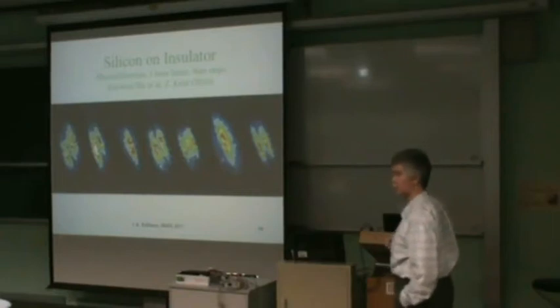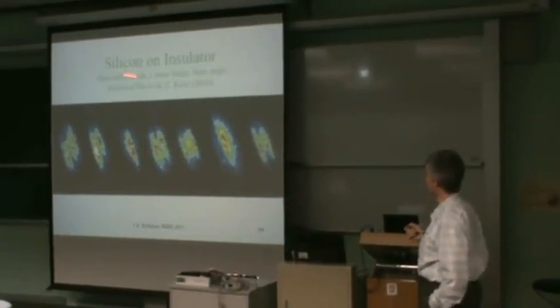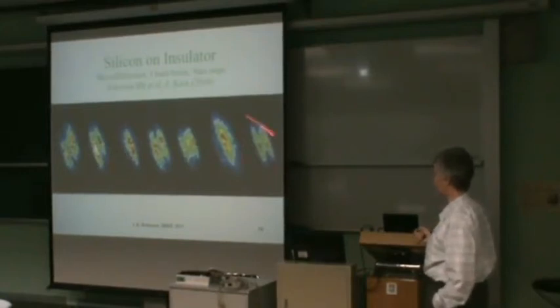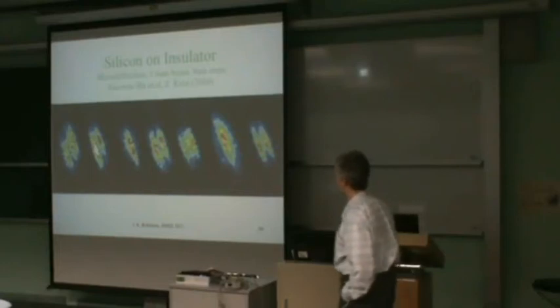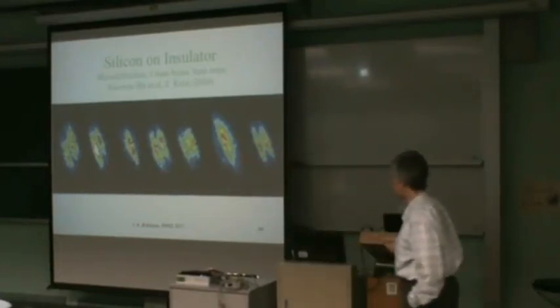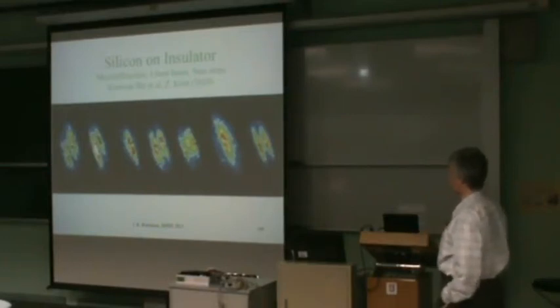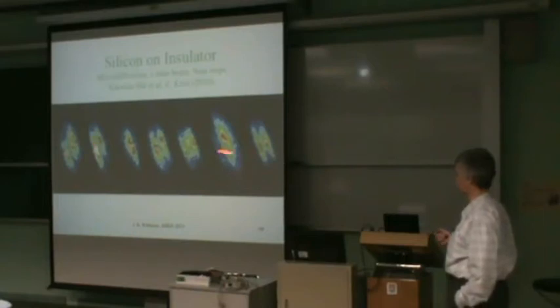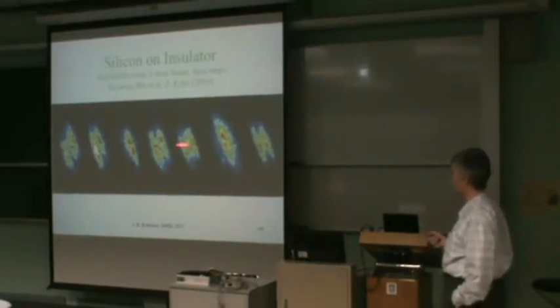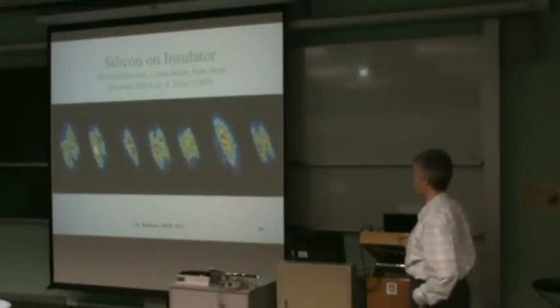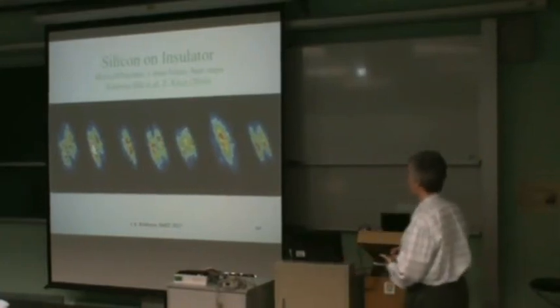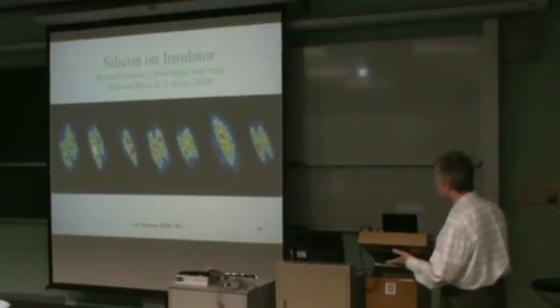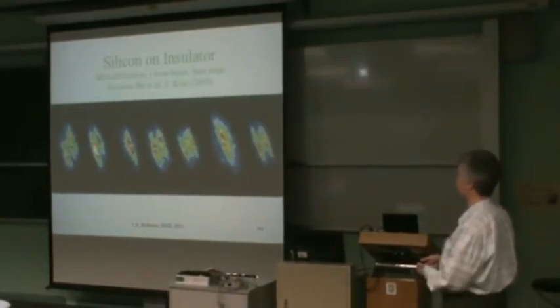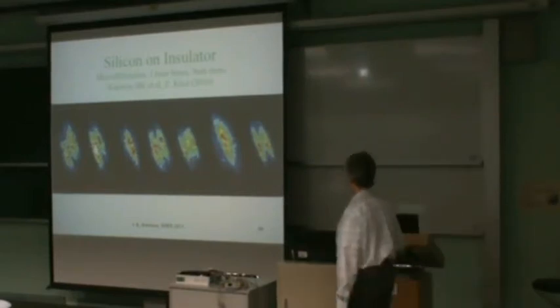The first thing she found, however, and this may be of interest to people in the room here, is that the SOI that we looked at, a blank piece of a blank wafer of SOI that we measured, showed something. This is the experiment that Connell talked about, where we just put a small beam on the sample and measure the diffraction pattern of one bright peak of the SOI. And what we found was that you almost never get a single bright peak. As you scan the beam along, you get split peaks, sometimes 3 peaks, sometimes 2 peaks. What it's showing is that the SOI is actually fairly defective. And this was just an observation of the SOI itself being relatively imperfect.